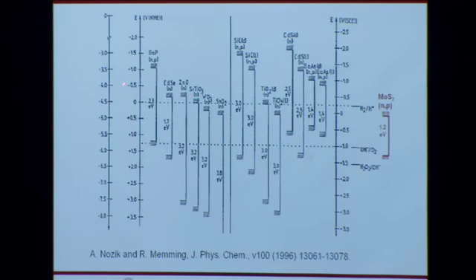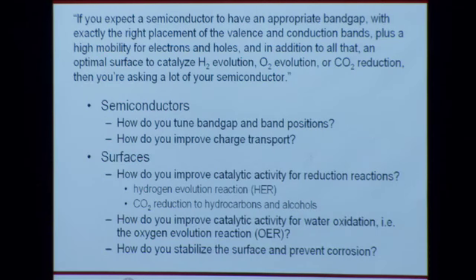Cadmium selenide is an interesting one. It has about the right bandgap of 1.7 eV and happens to straddle the bands, but it falls apart in solution. So that's no good either. We're going to be talking about molybdenum sulfide in a minute, so I just wanted to point out this is what its bandgap looks like. It's a bit small at 1.2 eV, and it's actually a little low with respect to the hydrogen evolution potential. So bear that in mind.